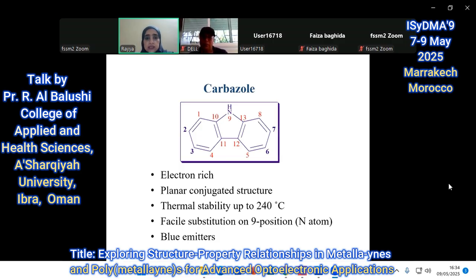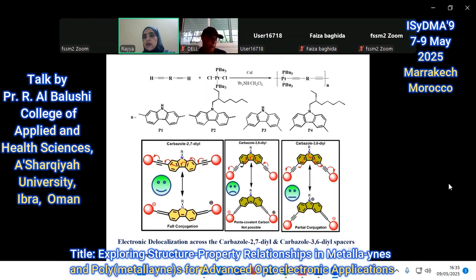We started with one of the spacer groups which we use, carbazole. And why carbazole? Carbazole is electron-rich and has a planar conjugated structure, and without any substituents it has a thermal stability up to 240. Another property is that it can be functionalized with different units at the nitrogen position, which is the 9th position, and carbazole materials are well known as blue emitters. So we thought that by incorporating this spacer group into our platinum polymer, we would have materials which are good for light emitting diodes.